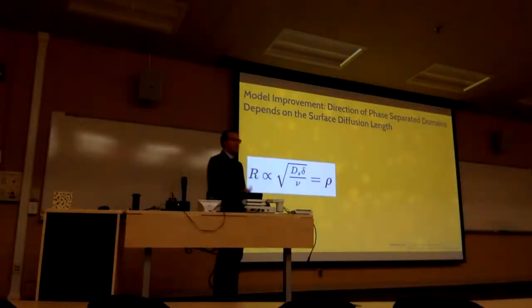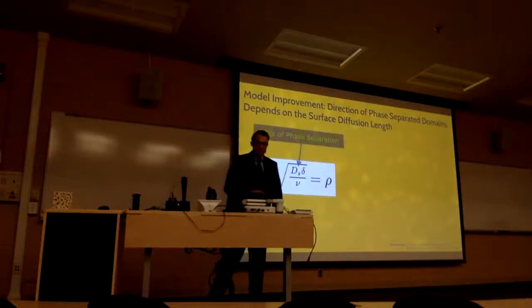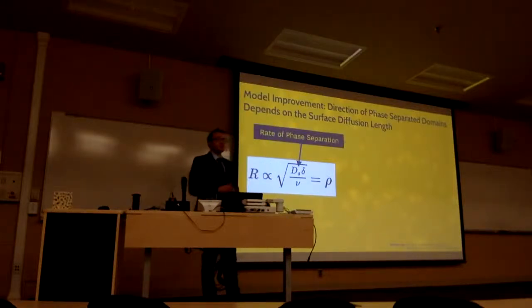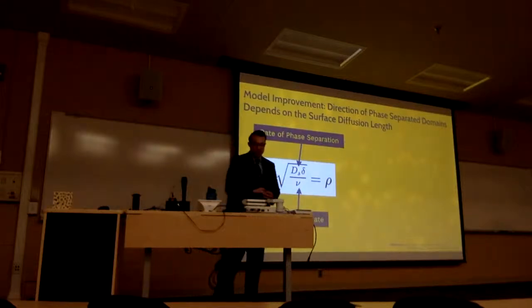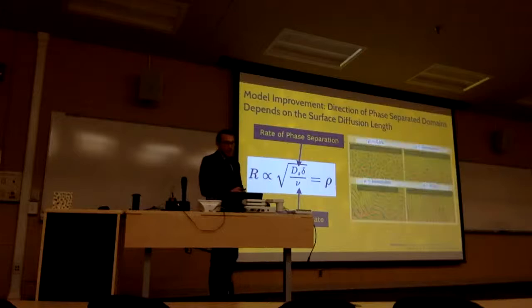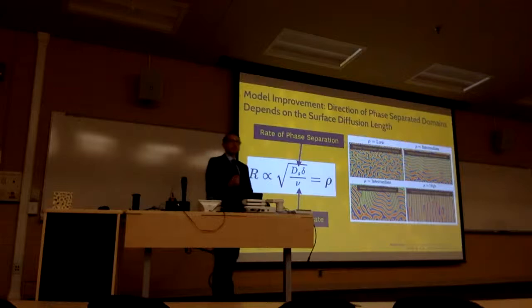So this model was actually later improved upon by a group at Ohio State led by Yunzhi Wang, which just saw this equation a little differently. They saw this equation as a competition between two different rates. The first rate being the rate of phase separation, and the second being the deposition rate during growth. And so the competition of these two rates can not only determine the size of the domains, but the direction of phase separation during thin film growth.